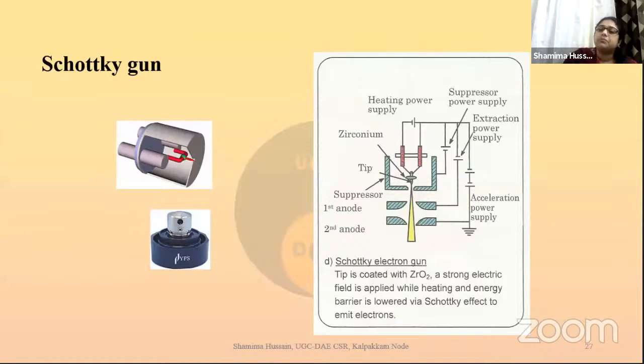Then we moved to the Schottky gun, and here also we had one problem. Since there were semiconductors, time and again there would be charge build-up, and we would have to clean it out. Cleaning it out means we would have to etch the surface, which was a very tiresome and cumbersome process. Breaking the vacuum, taking it out, cleaning it, and again putting it back, getting the vacuum again. So de facto, you would have almost a week of the microscope being off. So what we are currently using, all modern researchers, are these FEG-TEMs. In FEG-TEMs, we don't have to do all these things. We just have to give a high voltage.